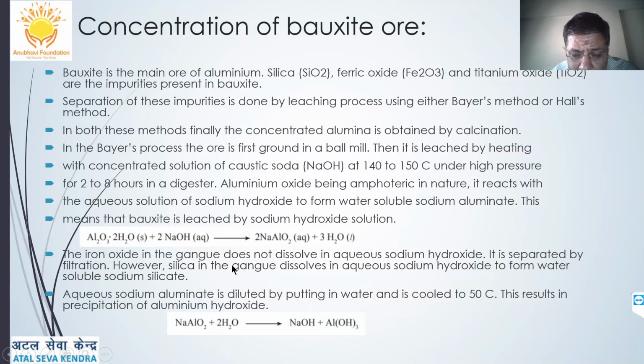The iron oxide in this gangue does not dissolve in aqueous sodium hydroxide, so iron oxide will separate out, and thus you can filter it out and you can get sodium aluminate. Sodium silicate also sometimes is there because it is soluble along with it. The next step: aqueous sodium aluminate is diluted by adding water and cooled to 50 degrees centigrade. So sodium aluminate reacts with water to form sodium hydroxide and aluminium hydroxide.